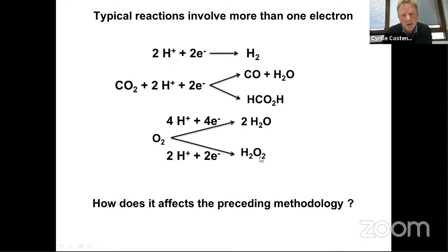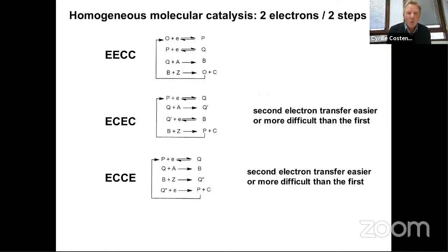And so the question might be, how does it affect the preceding methodology? Which kind of kinetic information will you get if you have several steps, if you obtain a plateau CV, for example? Well, actually, this is not a simple situation, because you have to consider the different 2 electron, 2-step possible processes. And here I won't go through the details, but you can have first electron transfer, then a second electron transfer, and then you generate your active form of the catalyst, and it's followed by reaction with the substrate, makes an intermediate, and then reacts with the co-substrate, for example, an acid, to get the final product and regenerate the catalyst.